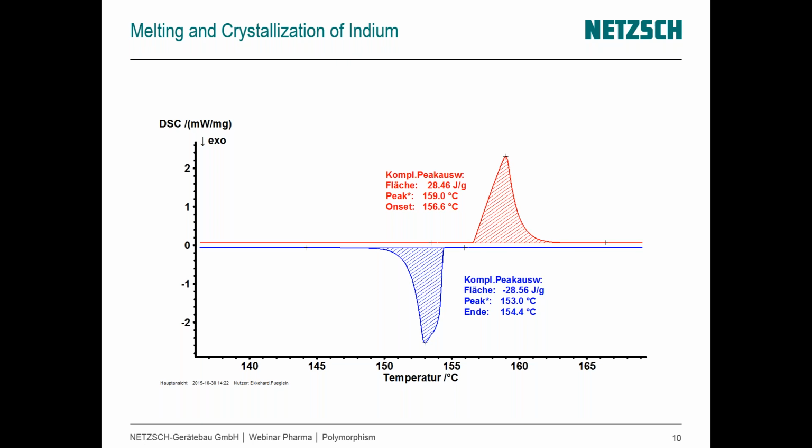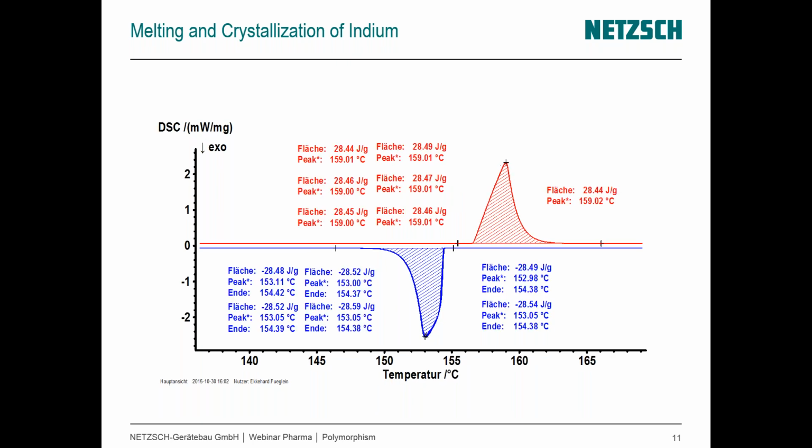If these terms are a little unfamiliar to you, the thermodynamic event is going to take place at the given temperatures, relatively independent of time scaling. However, when we go from the liquid to a solid, we're going through a crystallization. Crystallization is going to be time dependent. It takes time for those liquid molecules to orient themselves in relation to each other and form that crystal lattice. So that's why we're seeing this offset known as hysteresis between the onset of melting and the onset of cooling.